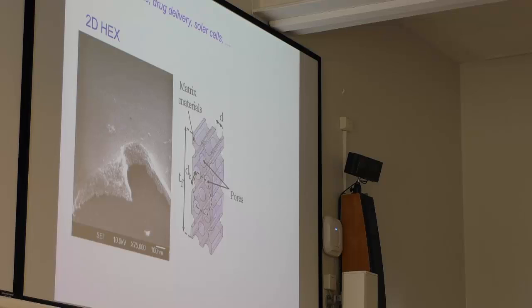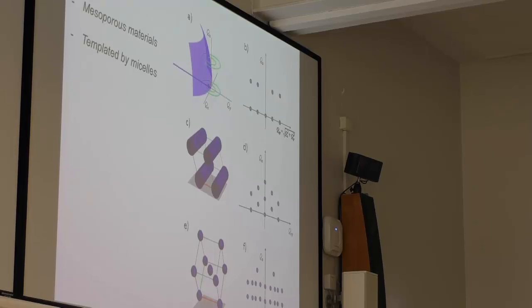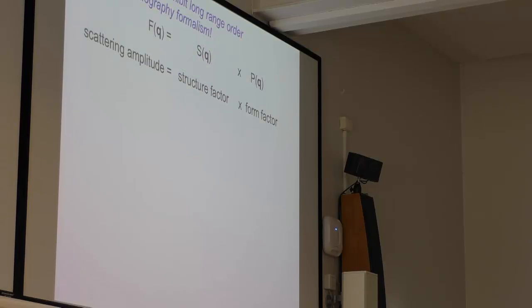So here is what that typically looks like if you look at the thin film using a scanning electron microscope. You can see that there are these extremely regular long-range ordered structures that can, for example, be hexagonally packed or also assume other structures like FCC packing, for example. Yeah, so all these packing patterns have their kind of reciprocal space or scattering pattern fingerprints, so that one can easily, or with some modeling efforts, distinguish between them. And as I said, these pores or micelles that are self-organizing here, they are doing this in a very regular manner. They are forming long-range ordered crystals.